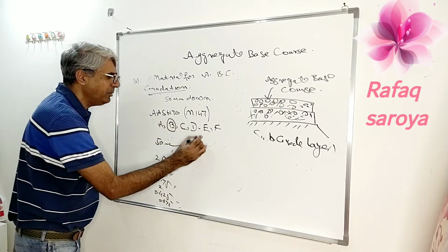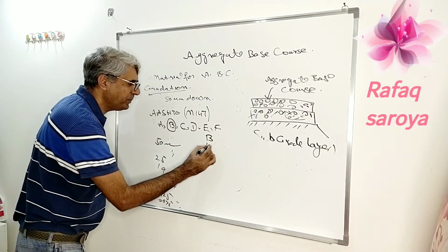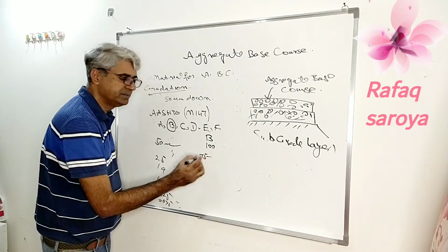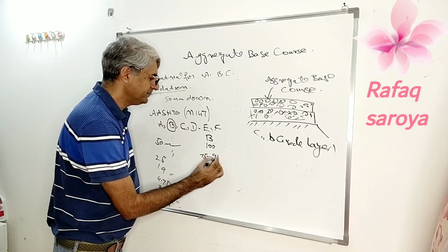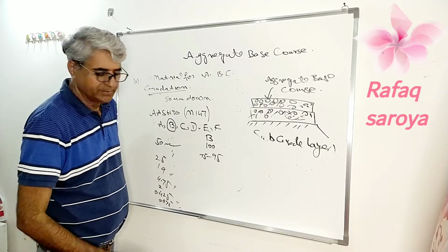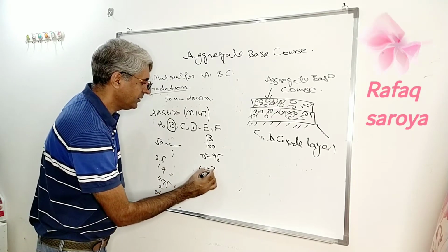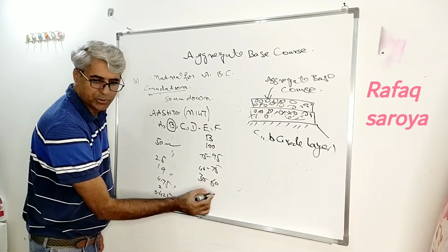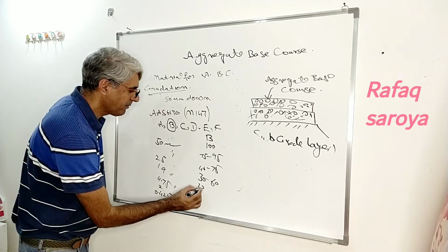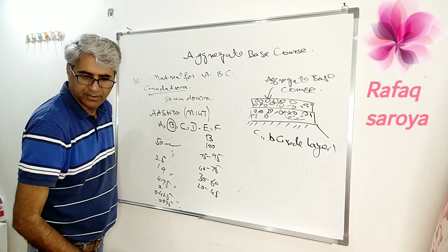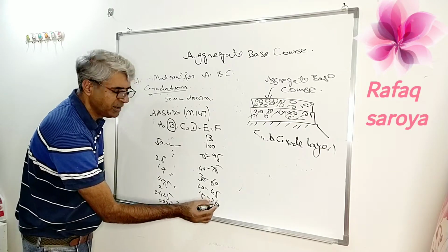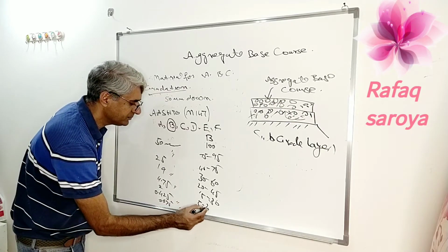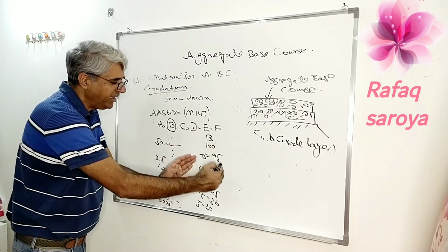And as I have told you, I am going to discuss this material. 100% should pass through the biggest one. The next, 75 to 95. Next, 40 to 75. 30 to 60. 20 to 45. 15 to 30, and 5 to 20. So this is my envelope.